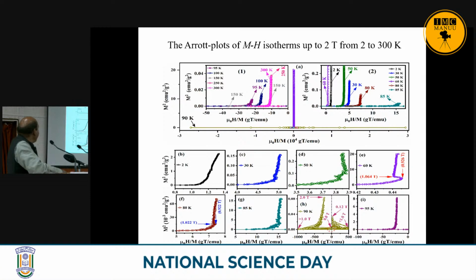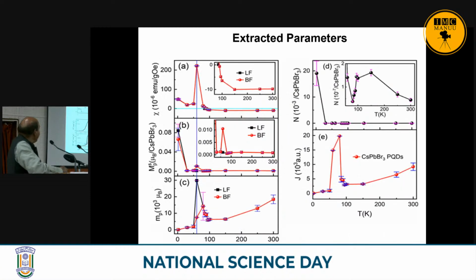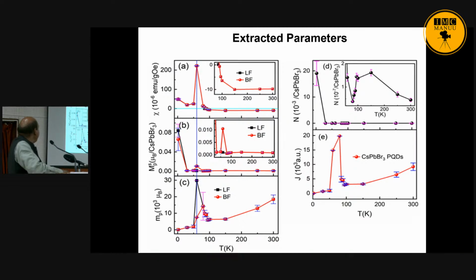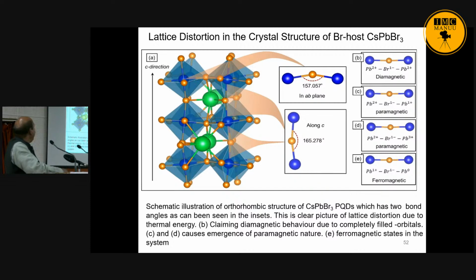Then we calculate, this Arrott plot is also confirming the same thing, but we calculate some parameters through some formulas. These are the different magnetic parameters. Then, with temperature, you can see the magnetic parameters showing some change, at 156 K. This change is coming due to some magnetic phase transition. The magnetic phase transitions are coming here, so these changes are also coming here. This is a huge change. How can we explain this? It is happening due to lattice distortion in the crystal structure of the host CsPbBr3. It means some lattice distortion is happening here.